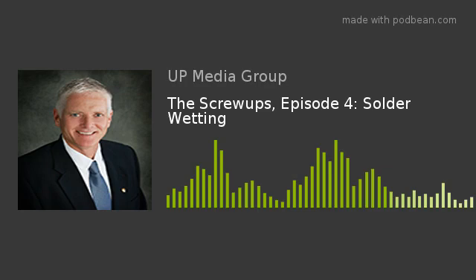So when we break down the oxide layer with the rapid heat of the soldering iron, we know that there is a solderable surface there, because sometimes components are just unsolderable. Whatever contamination is present simply will prevent wetting from occurring at all. And that happens from time to time. If you think about how a soldering iron gets heat into the component as opposed to how a reflow oven does, a reflow oven gets heat into the component in a very gradual way. It takes time, as opposed to the soldering iron that's essentially instantaneous. It's minutes in an oven versus seconds with the soldering iron. So that often is an indicator that we've got something here that we can work with.